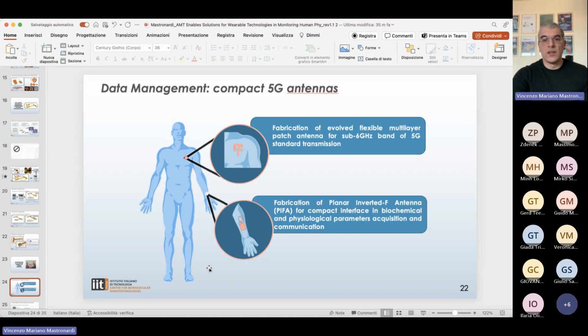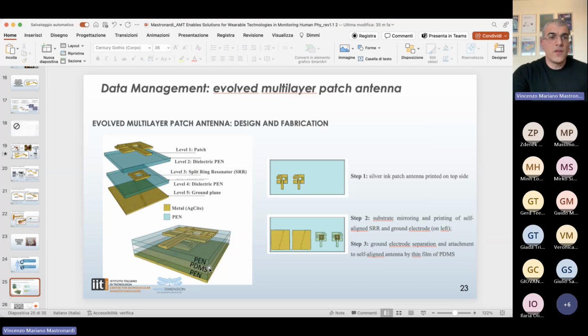The first antenna is an evolved flexible multi-layer patch antenna used for the sub-6 gigahertz band of the 5G standard transmission protocol. The second one is a planar inverted F antenna, called PIFA, that is more compact compared to the patch antenna. The first device, the multi-layered patch antenna, consists of two parts. The first consists of a patch and a split ring resonator directly built on a dielectric polyethylene naphthalate substrate, and the second part is the ground plane, still printed on the same PEN substrate.